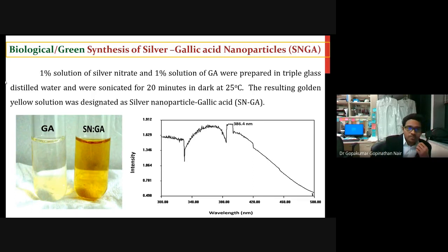So I have used this biological green synthesis of silver nanoparticle drug complex of gallic acid. I named it SNGA. So once the nanoparticles are formed, here I have used gallic acid and silver nitrate solution, 1% silver nitrate solution and 1% gallic acid, which was procured from Sigma, I think. And I have ultrasonicated it in triple glass distilled water, sonicated it for 20 minutes, and kept it in the dark at 25 degrees centigrade.